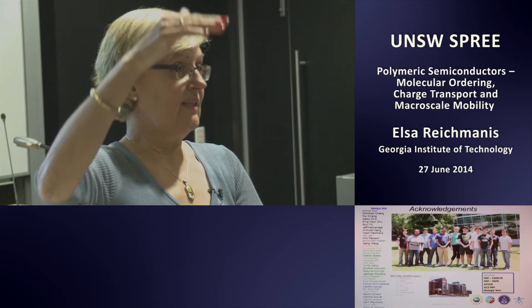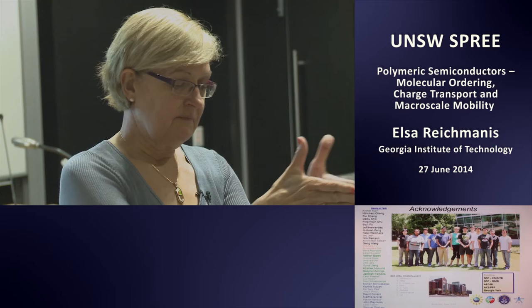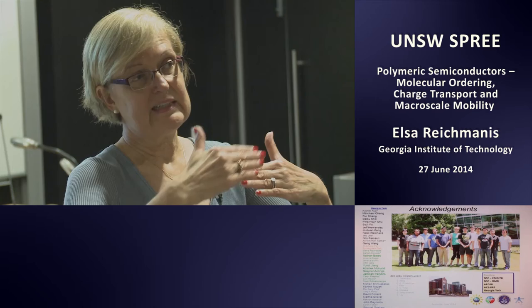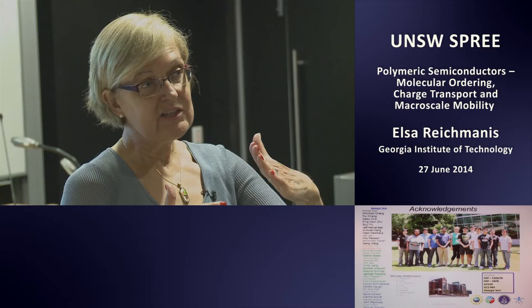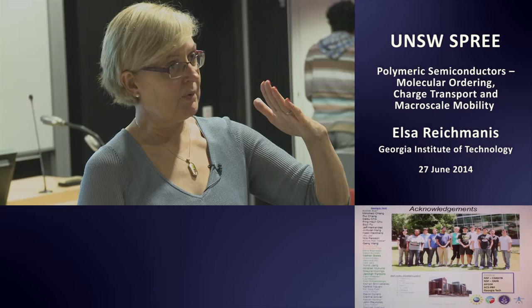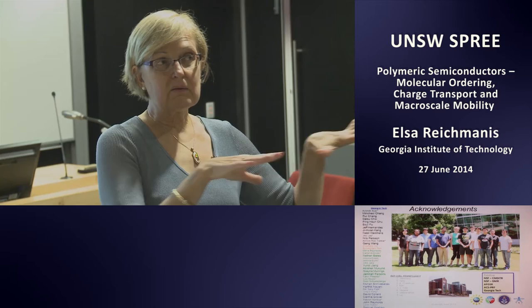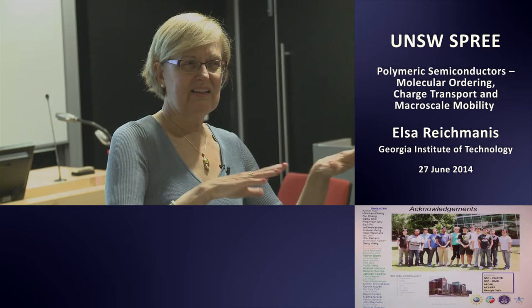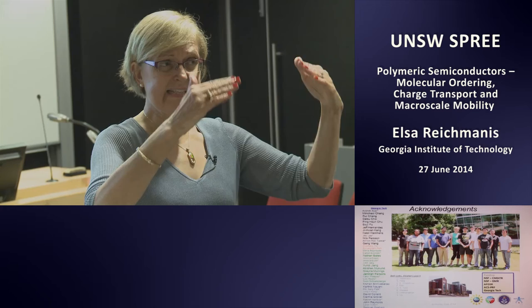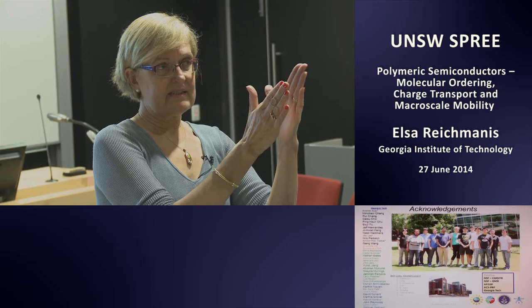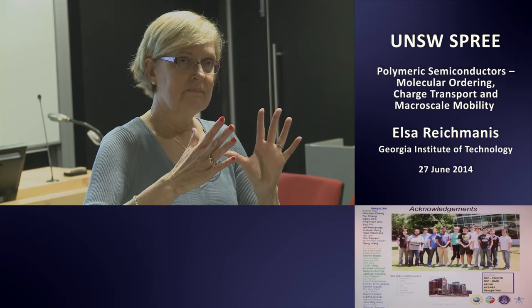I was personally a little surprised that having as much as we had, the mobility actually is good. And I think that's because charge is strictly transported at the interface between the dielectric and the semiconductor. And I suspect that it has something to do with the orientation of the semiconductor on the substrate. It's probably not perfectly vertical. It's probably somewhat angled. And the spaghetti somehow interacts in order to maybe have some dielectric character to it. And since it's that interface layer that's important, it's really the pi-pi stacking at that layer that's going to be important as opposed to what's above it. So it's not known is the short answer. And the other was the long-winded answer.